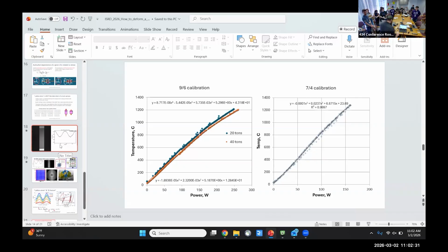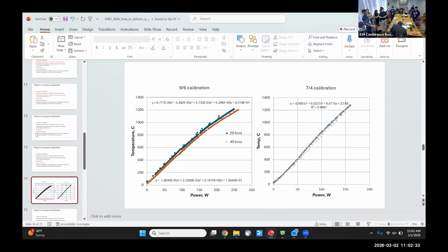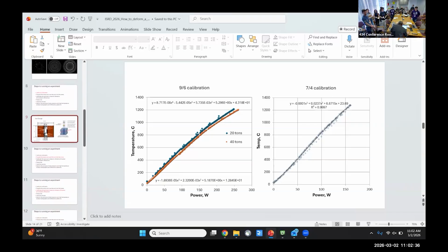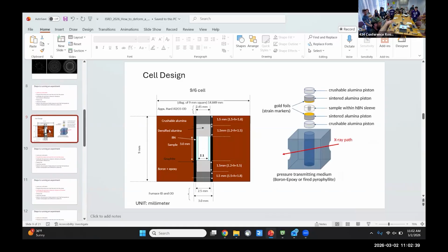Another thing that I should mention, if I go back to our cell design here, we have very large thermal gradients in our sample. So at the center, which is usually where we put our thermocouple for our temperature calibration experiments, let's say it's 1,000 degrees right at the center, it might be 900 degrees a millimeter away. So we have large thermal gradients within our samples, and it's really bad as you go up vertically. It's not so bad radially unless you go outside the furnace, then it drops off dramatically quickly.